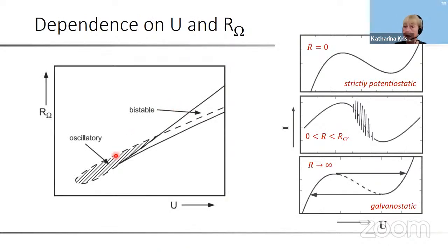Again, in which parameter range do we expect the behavior in now our N-NDR oscillators? We have already seen how the bistable parameter range opens towards large values of U and R, and oscillations are usually found in a small loop around this cusp point. So the oscillatory region is not very large.